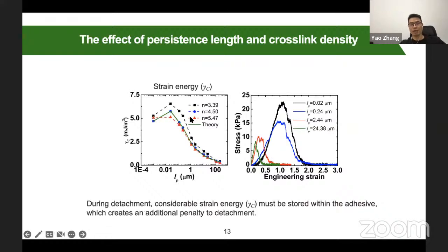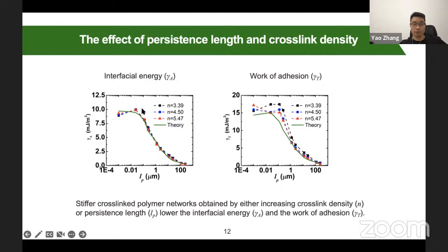And also, we try to explain the difference between the interfacial energy and the work of adhesion. If you compare the interfacial energy and the work of adhesion, you can see the maximal work of adhesion is around 15 millijoule per meter square. You can see that its magnitude is always larger than the interfacial energy. So you have a force trying to detach the network from the surface, and the work you have done is always larger than the interfacial energy. So why? We try to understand it.